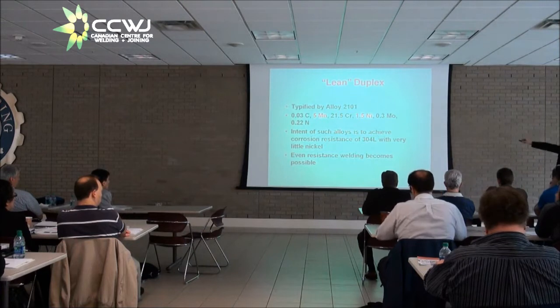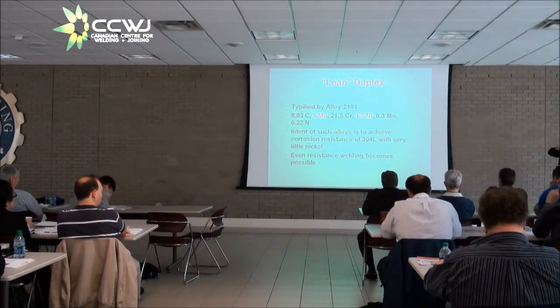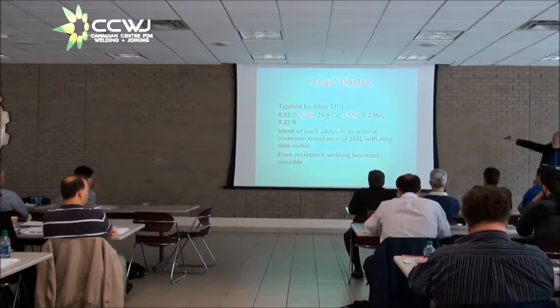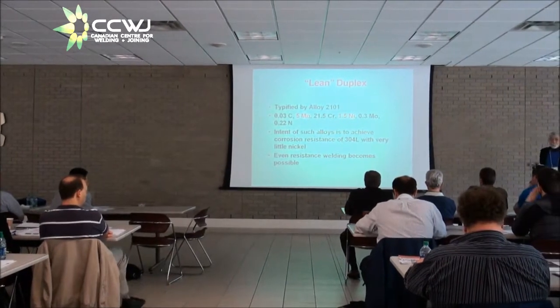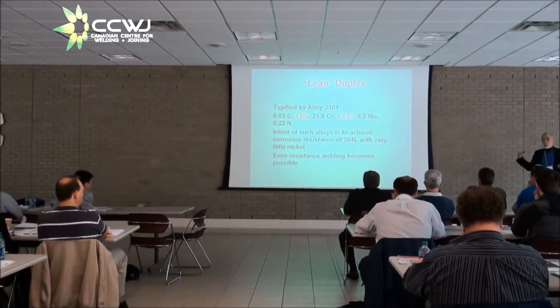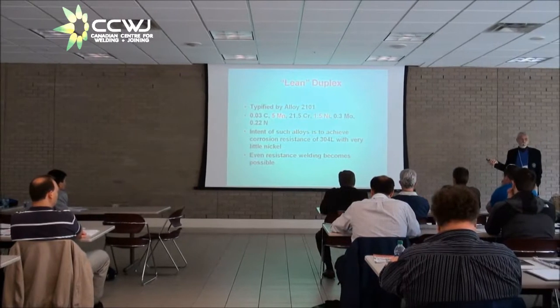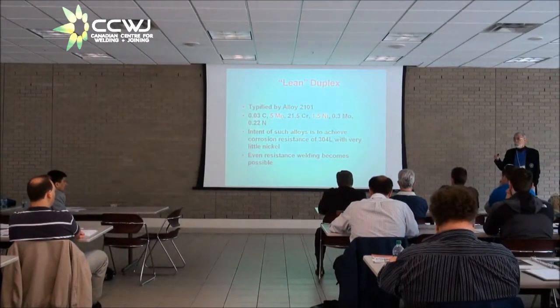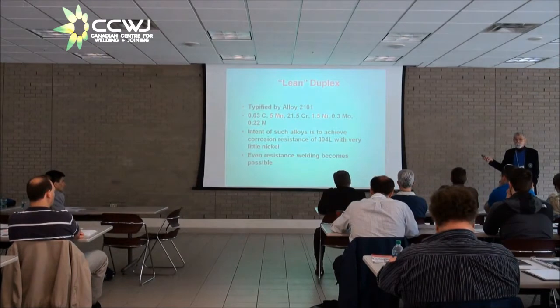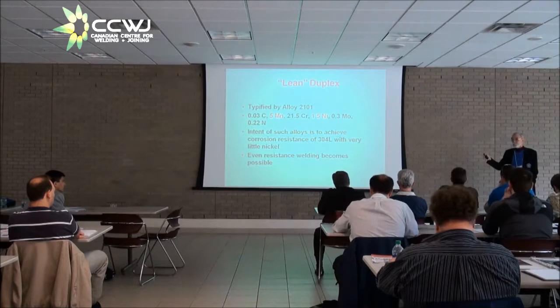This alloy is very low in nickel, only 1.5% nickel, but it's got 5% manganese in it. Now the function of the manganese is not to promote austenite. You have to get that notion out of your head. Manganese does not promote austenite. Those of you who know the Schaeffler diagram and see manganese in there as an austenitizer, get that out of your head. It doesn't do it.